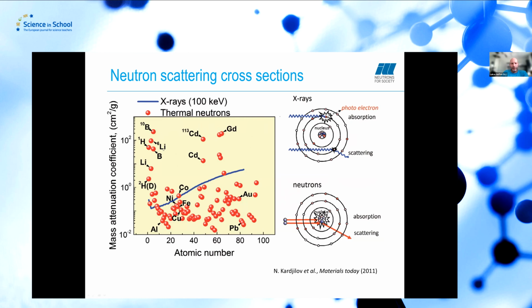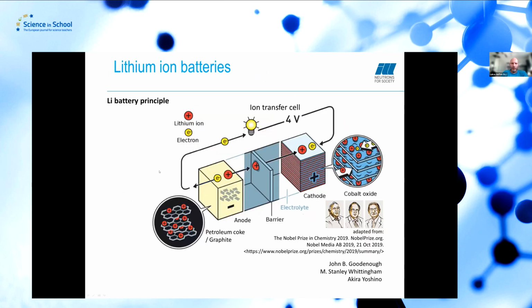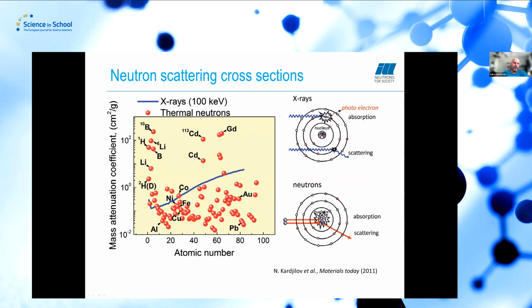And here Alessandro has mostly shown things on hydrogen and water. I will go more here into lithium and the distinction of lithium from its surroundings, where we see that with X-rays, if you have carbon, for instance, or hydrogen, nitrogen, oxygen inside a component or in a material, then you can very badly distinguish them from one another. And with the neutrons, we are well sensitive to the lithium due to its high attenuation coefficient.